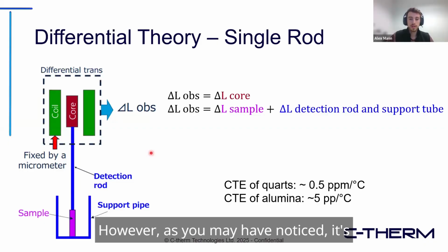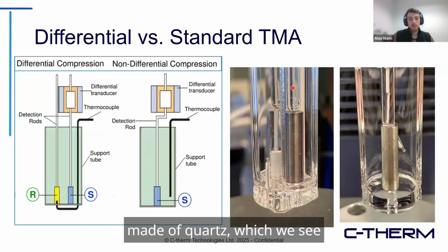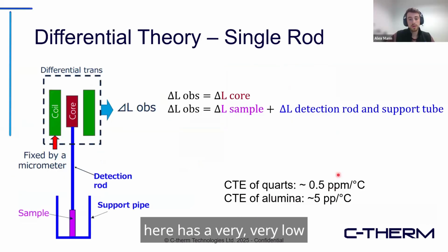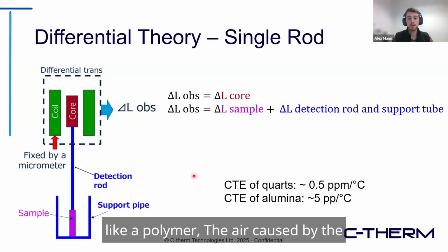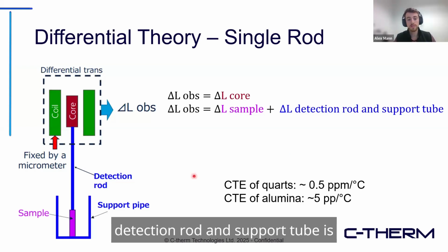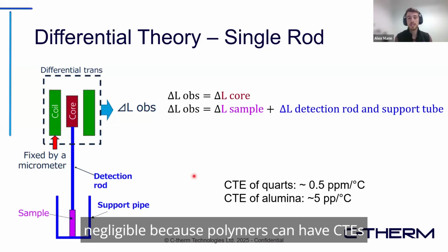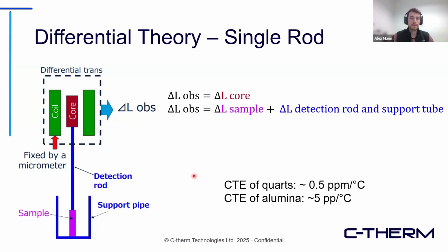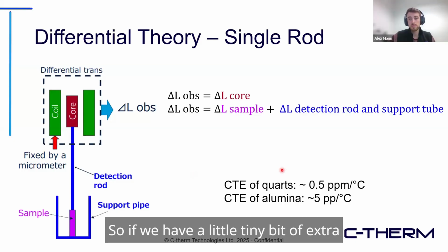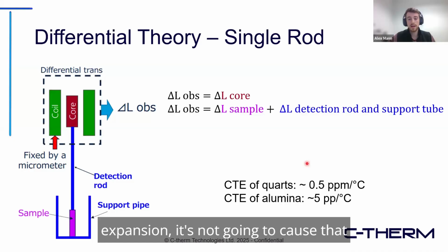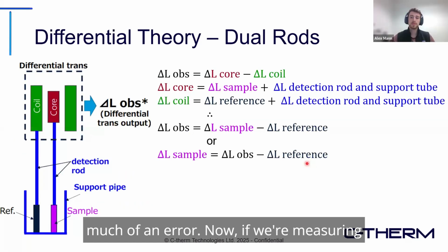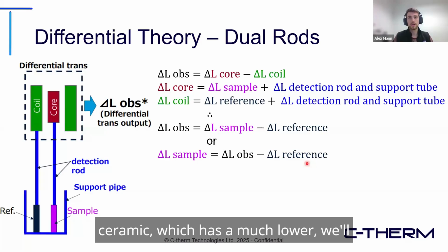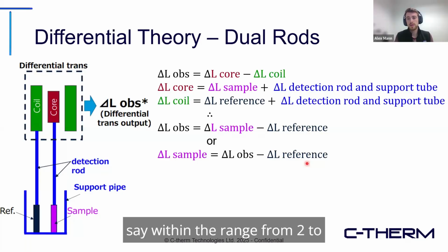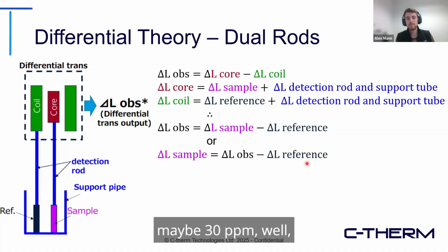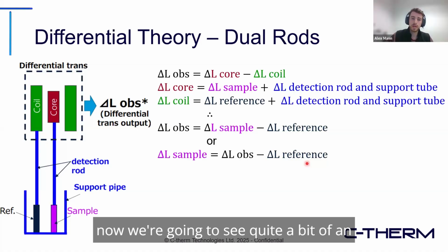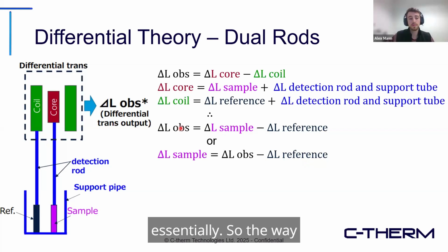However, as you may have noticed, it's made of quartz, which we see here has a very, very low CTE. So when we're measuring something like a polymer, the error caused by the detection rod and support tube is negligible, because polymers can have CTEs on the order of 200, 300, 400. So a tiny bit of extra expansion isn't going to cause much of an error. Now, if we're measuring something such as a glass, metal, or ceramic, which has a much lower CTE, within the range of 2 to maybe 30 ppm, we're going to see quite a bit of error due to the expansion of the setup.